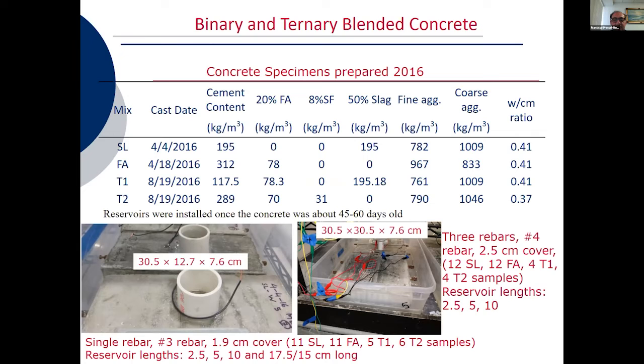In this case, it was a 30 by 30 top cross section with a thickness of 7.6 centimeters. You can see that 4 compositions were prepared. Some of them contain only blast furnace slag in a ratio of about 50%. Others contain 20% fly ash. Then we have ternary mix 1, which contains both slag and fly ash, and another one, T2, which contains fly ash and silica fume. The water to cementitious ratio for the first 3 was about 0.41, and the last one, T2, had a water to cementitious ratio of 0.37.